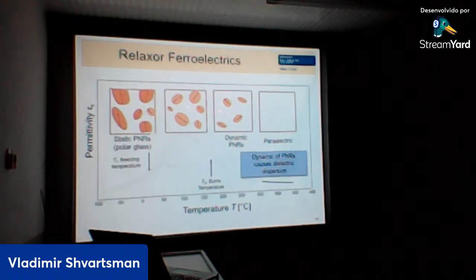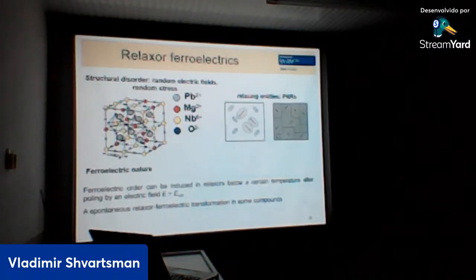So on cooling, they slightly grow, and they start to feel each other. They start to interact, and finally, the dynamics of the PNRs slows down, and this peak of the dielectric permittivity which is observed is actually related to the slowing down of the PNR dynamics. And finally, below the so-called freezing temperature, they become frozen. And we need a really hard, large electric field to move them. And in some cases, we can induce a transition to the ferroelectric state, but in that case, this transition will be irreversible.